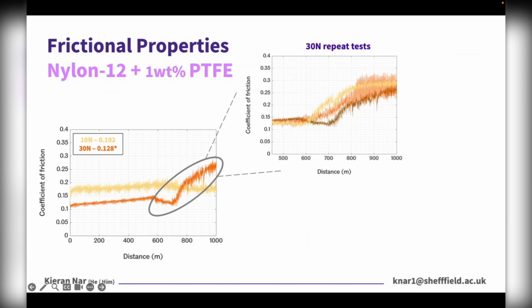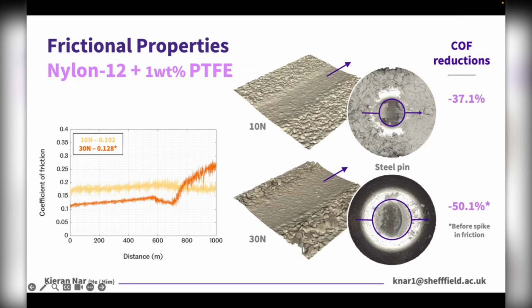So it's likely that resultant thermal softening led to the steel counterface further indenting the PTFE PA12 surface, which will have meant that greater ploughing will have ensued, and as a result, friction will have increased. However, prior to this spike in friction, we found that the addition of PTFE reduced coefficient of friction by as much as 37% and 50% during 10 and 30 Newton sliding, which we attributed to the formation of a lubricating transfer film, which is very characteristic of PTFE.